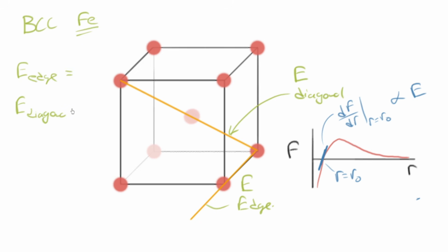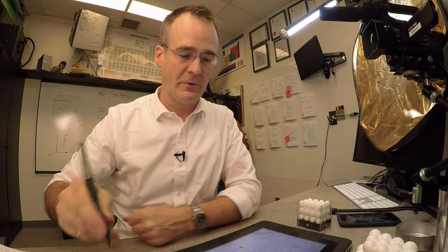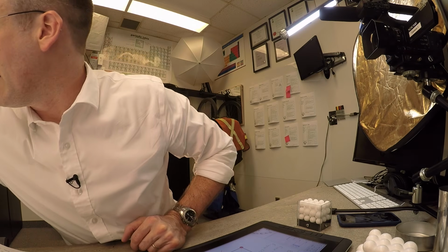And that is, in fact, correct. Along the edge, it's around 125 gigapascals, and along the diagonal, it is 273 gigapascals. So huge difference, and we can explain it with some knowledge of crystal structure. Okay, let me give you another example.